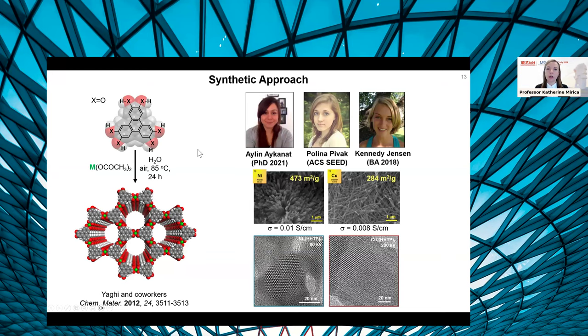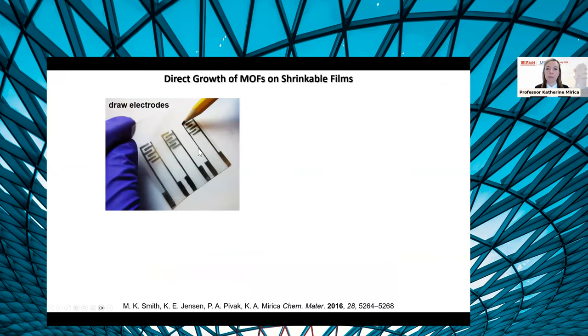So I want to start with one of the simplest approaches that my group has implemented by directly growing conductive metal organic frameworks on shrinkable polymer films. So this is a very simple device architecture where we can simply draw graphitic electrodes on a shrinkable polymer film. This is just a pre-stretched polystyrene. And we reasoned that this would have a couple of advantages for device fabrication.